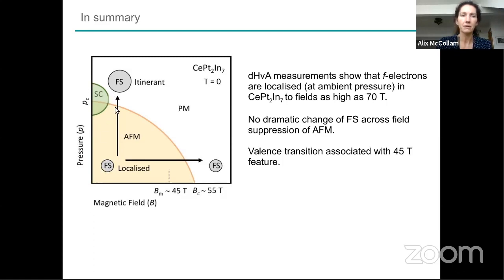It's understood that there's a transition here at the critical pressure. One question about this transition: NMR, as well as transport, shows some disagreement about whether the Fermi surface transition happens exactly at the critical pressure for suppression of antiferromagnetism. I think the Fermi surface transition is thought to happen at slightly lower pressure, maybe even slightly within the antiferromagnetic state. That's the only unresolved question I'm aware of regarding large to small Fermi surface at low field. But in principle, an ARPES measurement should tell us perfectly well what the Fermi surface looks like at zero field. Okay, a quick second question.